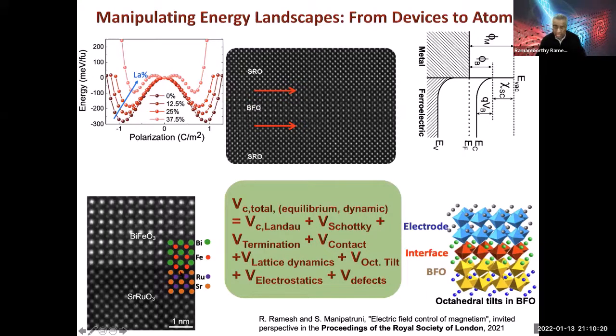Now, a long time ago, 10 years ago, one of my students, who is now a big professor at Tsinghua, Pu Yu, showed that if I have an epitaxial interface between strontium ruthenate and BFO, depending on the termination of the strontium ruthenate, whether it's strontium oxide terminated or ruthenium oxide terminated, you could have different built-in potentials of the order of 0.6 volts, very large shifts in the potential because of just the termination. LAO-STO is a nice example of that as well. And another aspect that I'm going to show you one piece of data on is something that the ferroelectrics community has never paid attention to, which is what happens to these octahedral tilts, or particularly what happens to mechanics.